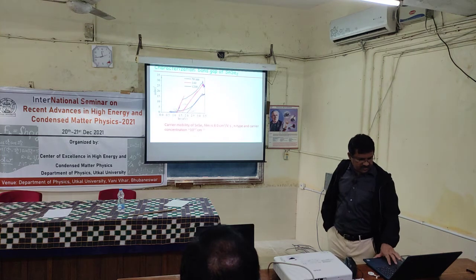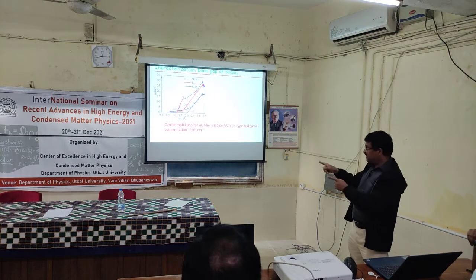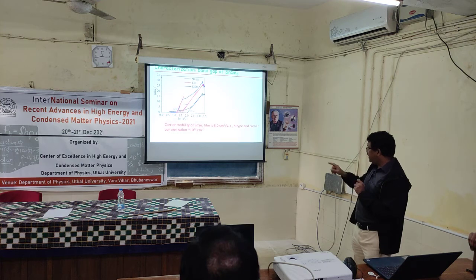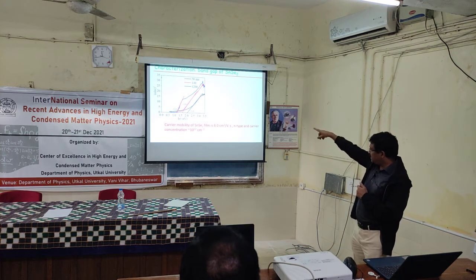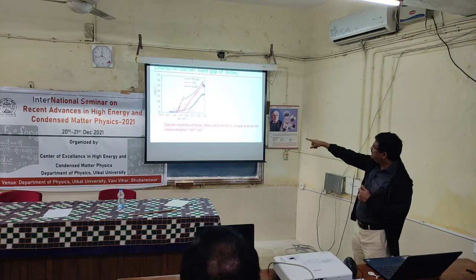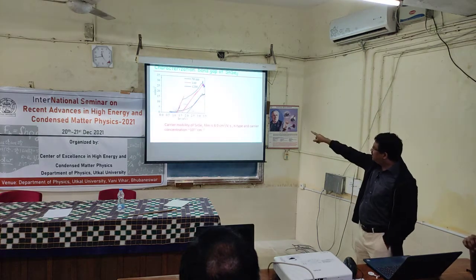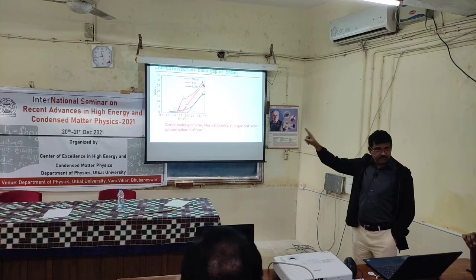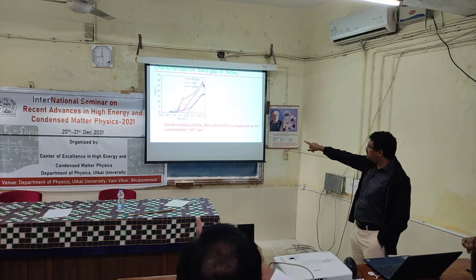So what is important here? I am taking the example of this thick film. But by changing the thickness of the film, as you can see, the band gap can be changed. Band gap will be tuned. For 1200 nanometer, it is 1.2 electron volt, as reported in the literature for bulk SnSe2.